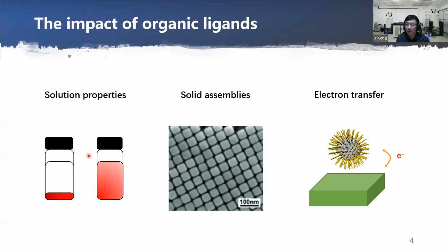In fact, the ligands are just as important as the core, because the ligands control solution properties, such as solution dispersity, and they determine the self-assembly in the solid phase and affect the electron transfer between the nanocrystal and the substrate. And because the ligands are flexible and disordered, there are very few techniques that can provide direct characterization, but NMR.